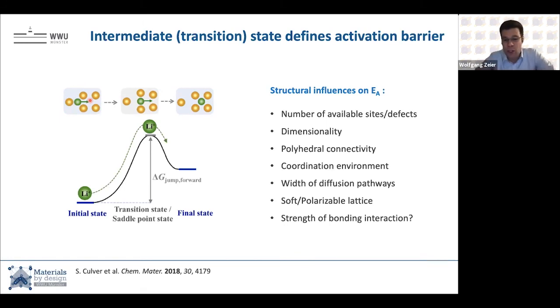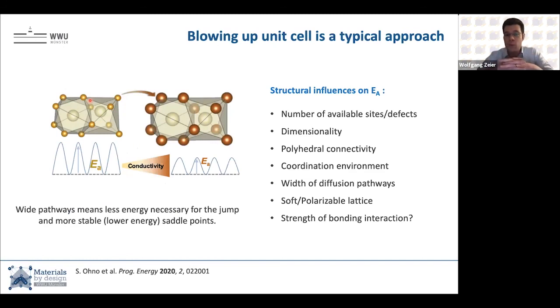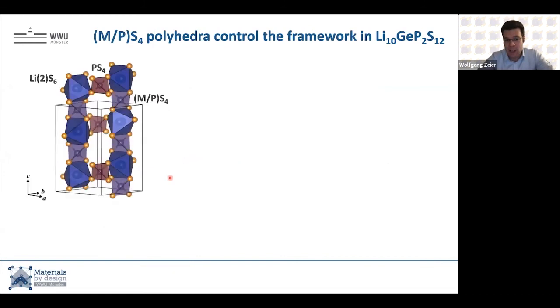And one of the typical approaches to affect ionic conductivity is to increase the width of the diffusion pathway. So if this bottleneck that I just showed is intrinsically larger, it may cost a lot less energy for this jump to overcome. And so what we usually do in ionics is we try to blow up the unit cell via substitution. Schematically, this is shown here: by a wider cell, we should have a lower activation barrier and higher conductivity. But then there are also questions like polarizability of the anions, and especially how bonding interactions change within materials. And this is something I want to talk about today. But let's focus on this idea that if we increase the unit cell size, the conductivity should change.